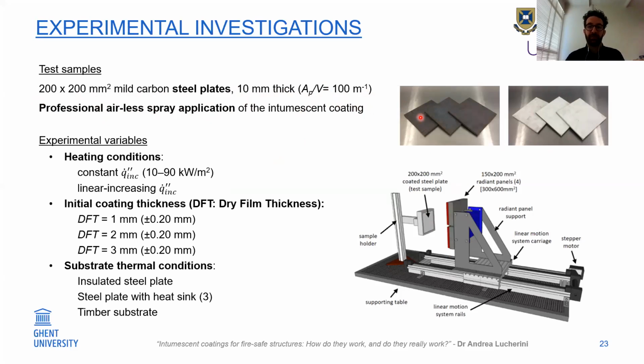In my experimental study, I focused on 3 different aspects. The heating conditions: I applied constant incident flux within the range 10 to 90 kilowatt per square meter, and linearly increasing incident flux. Different initial coating thicknesses, mainly 1, 2, and 3 millimeters. And different substrate conditions: a steel plate insulated at the back, a steel plate with a heat sink at the back, or a timber substrate, where I apply the intumescent coating on timber. And here you can clearly see the experimental setup.